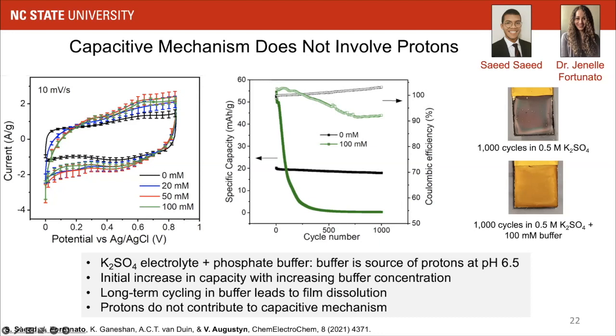However, this increase is very transient. It only occurs for the first few tens of cycles before the capacity degrades very significantly. Whereas if there's no buffer in the electrolyte, you get this lower capacity, but much more stable cycling. So what we observed here is that this film was basically dissolving when we had buffer present in the electrolyte. So protons did not contribute to the capacitive mechanism that we're talking about here when there's no buffer present in the electrolyte.